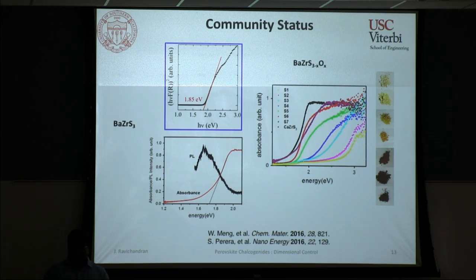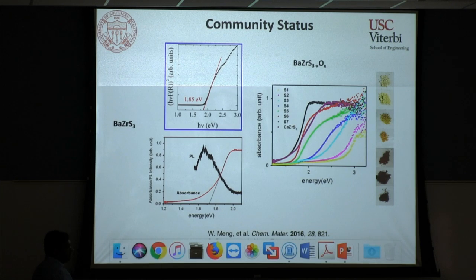While we were working on these, there were a couple of other reports that came out where people took the equivalent oxide materials and tried to use an extremely aggressive sulfurization mechanism using CS2 to get powders of these materials. As you can see, these are fairly successful, but it's very defective material, and you can see the PL curve for some of these materials does not look as impressive as typical III-V wafers look like.